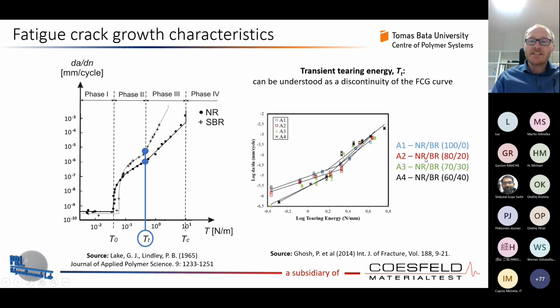What we did once is what was presented by a colleague, Dr. Ghosh, and in 2014 we published a paper where we investigated blends. These were NR/BR blends, pure NR, and then NR/BR 80-20, 70-30, 60-40. If we really focus on the detail, we will see that in pure NR there is more or less no transient point. However, once the BR content increases, the transient point will be more dominant with increasing BR content.